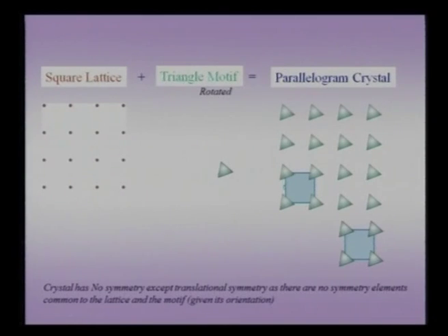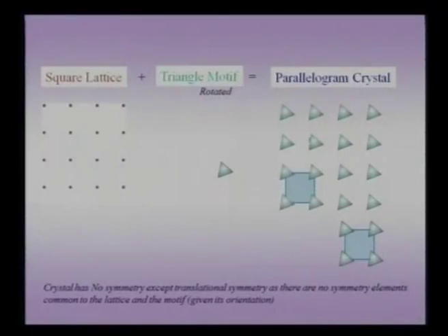The unit cell, as before, continues to be a square unit cell, as for the lattice and for some of the crystals we have generated before. Again, the choice of the unit cell is left to us. Even for the same crystal, I could make a choice of the unit cell. For instance, I can start from this lattice point, go here, go to this lattice point, and make a unit cell like this. So this choice I could make, though the preferred unit cell will still be the blue colored unit cell, and you can see that the red outlined unit cell is a doubly non-primitive unit cell, and this choice I can make.